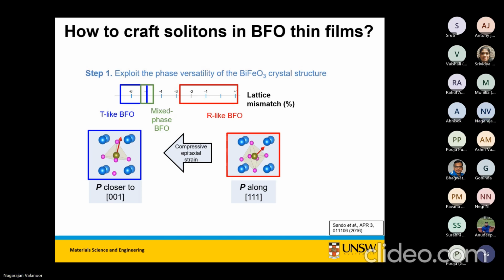It's possible. Now, the challenge here is, normally, you put it on a lanthanum aluminate substrate, within 5 nanometers, 7 nanometers, you got nucleation of the mixed phase domains. They relax that strain. That strain cannot be relaxed. Under no condition should that strain be relaxed by this ferroelectric or nucleation of the mixed phase. I wouldn't say ferroelastic, but this other strain relaxation mechanism.